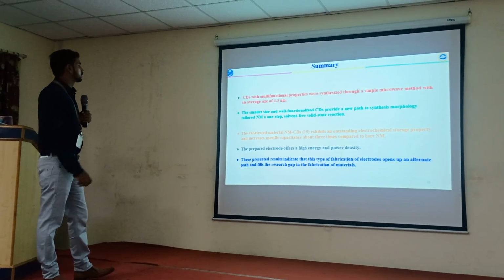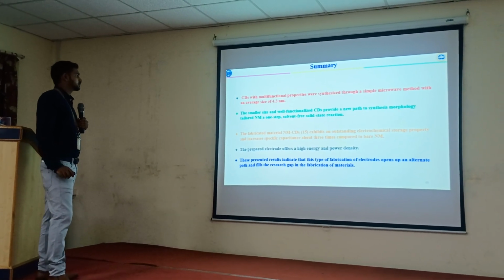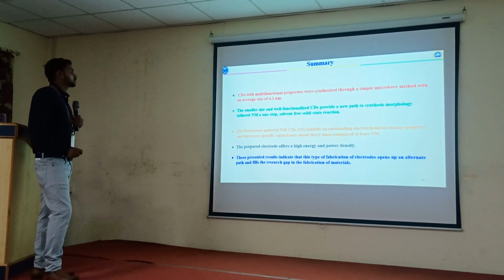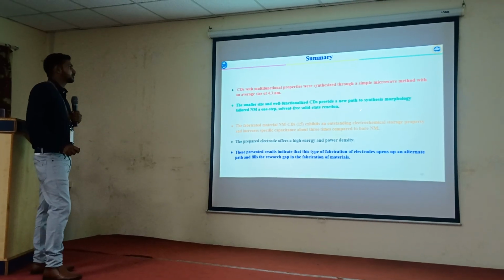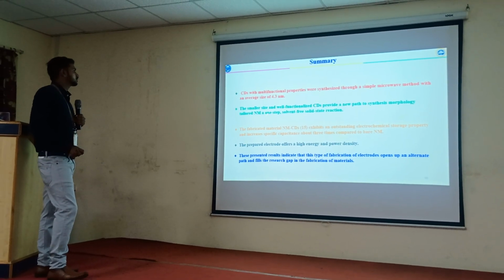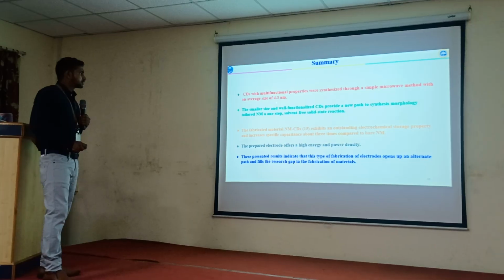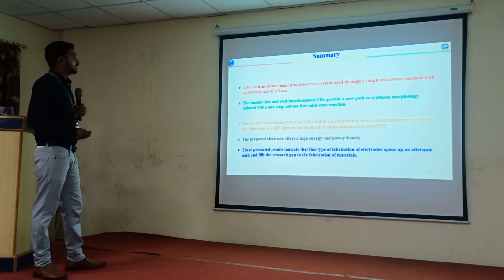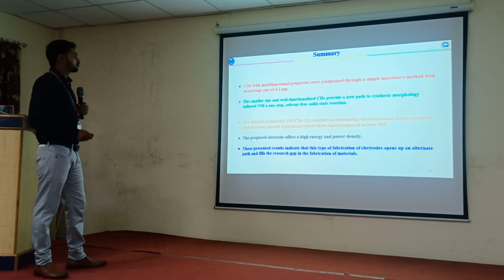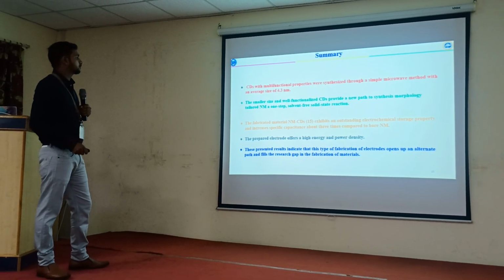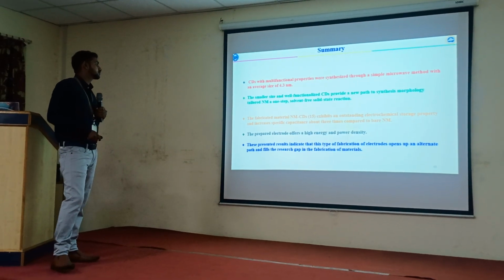And the summary of this work: carbon dots with multifunctional properties were synthesized through a simple microwave method with an average size of 4.3 nanometer. The smaller size, well-functionalized carbon dots provide a new path to synthesize morphology-tailored nickel molybdate with a one-step solvent-free solid-state reaction condition. The fabricated material with the carbon dots exhibits outstanding electrochemical charge storage property, with a specific capacity 3 times higher compared to bare nickel molybdate.